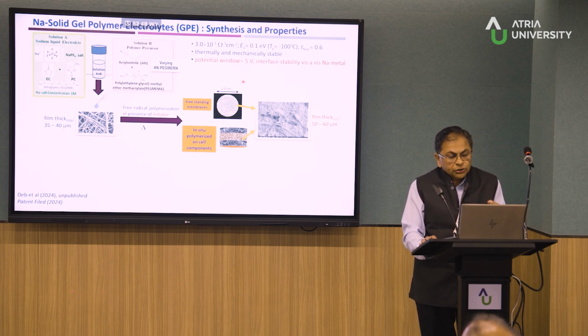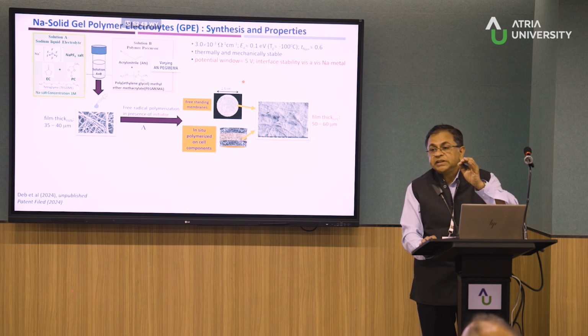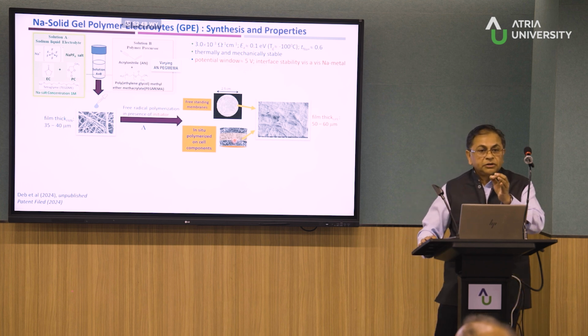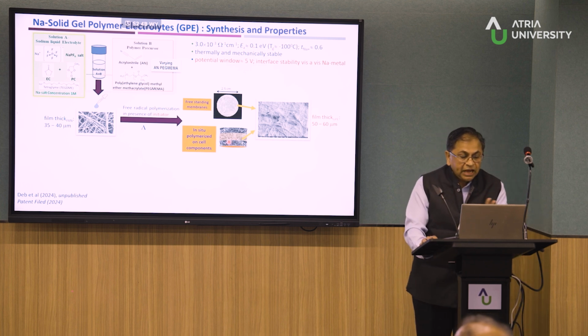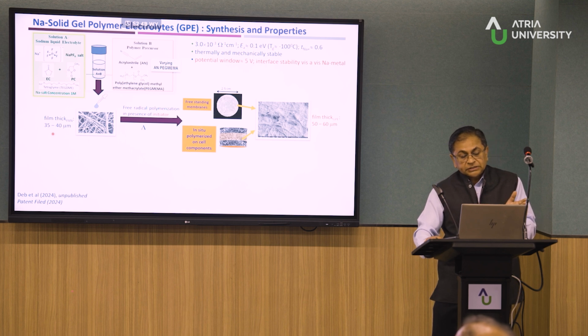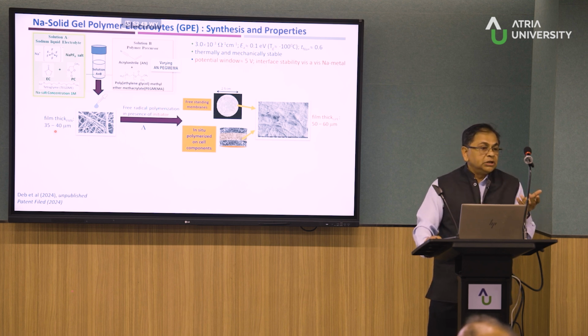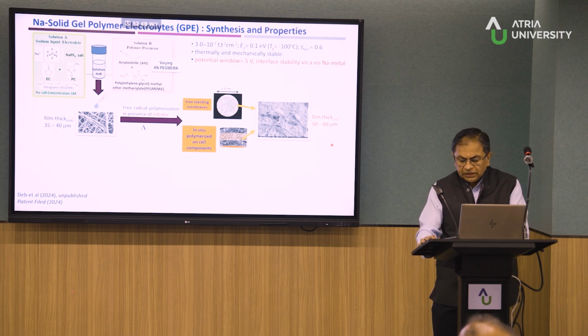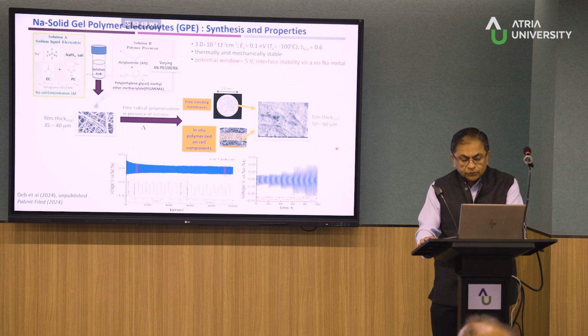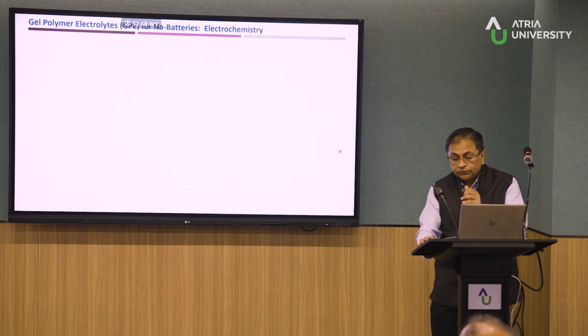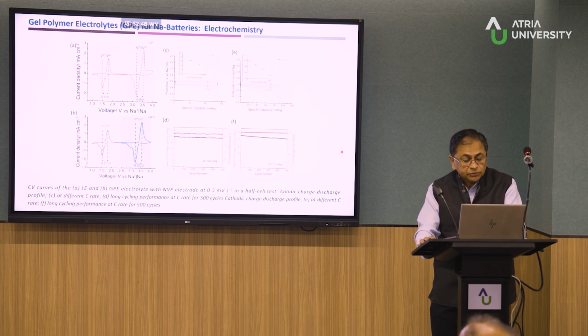Is that instead of just generating freestanding films, why don't we actually polymerize directly onto the cathode or the anode? And as you see, we're getting very good thickness. These are the kind of cell, polymer membrane, thickness that you get. They're very stable, and you can of course plate strip for very long hours. And the most interesting thing is that you can run it with various types of sodium battery electrodes. And of course, the one that I'm going to show you is this is with NVP.